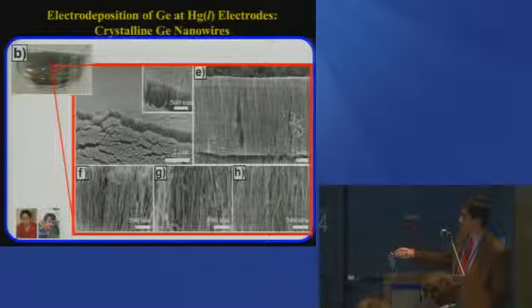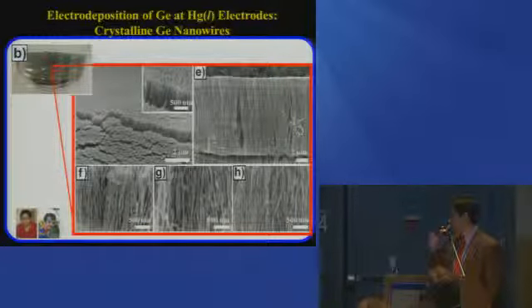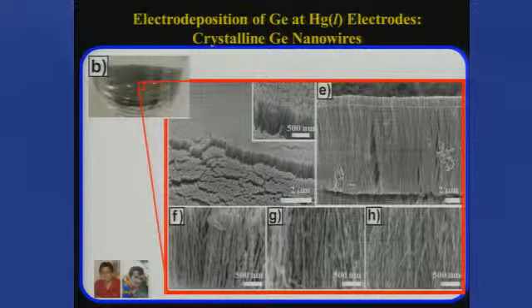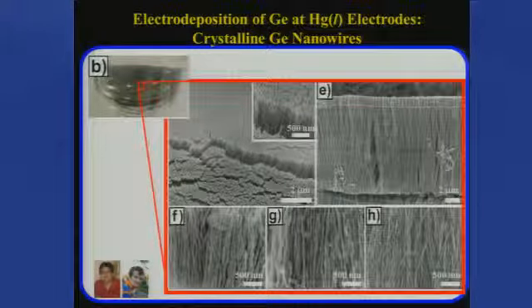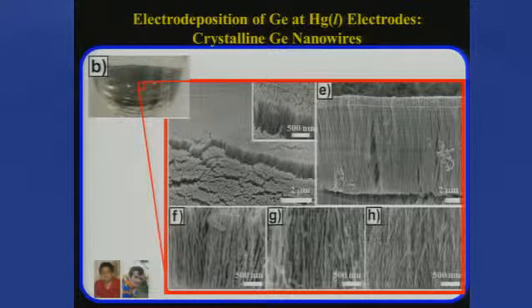Okay, this is a cross-section of what this looks like on a microscopic level. This is a cross-section of those germanium nanowire films. In this initial pass, which was done actually by a couple of really talented undergraduates, the subtle features of the diameter were a function of some parameters of the process, but essentially what matters the most is the length. The amount of material was dictated by the time of the electrodeposition.